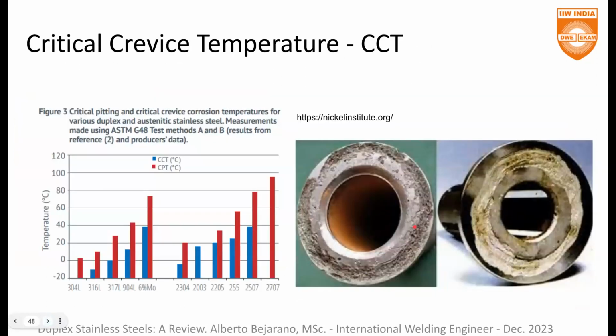Let's check this graphic, which is very interesting. In red, you see the CPT, which is the critical pitting temperature, and you can see in blue the CCT, which is the critical crevice temperature. So this word critical means that at this temperature we will have certainly pitting and certainly crevice corrosion. But what's the problem?